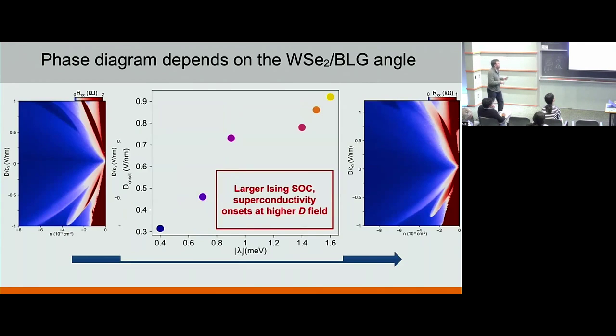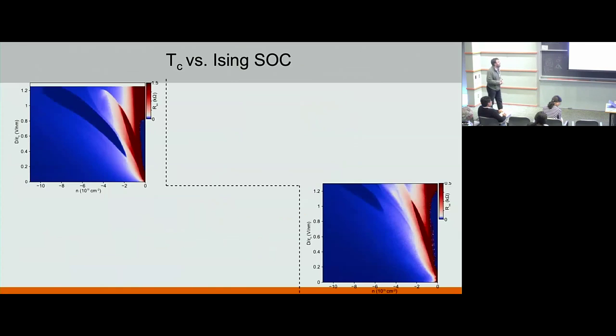And you can summarize this with this graph where you have strength of spin-orbit coupling on the x-axis and displacement field onset, like the tip of this superconducting pocket, on the y-axis, and you can see how this actually goes. So now I can give you the two examples. Now, this is the smallest spin-orbit coupling, 0.4. I think this is the largest, I think it's 1.6 meV.